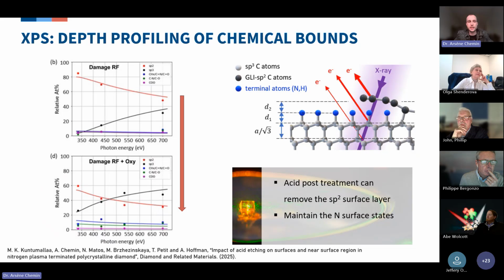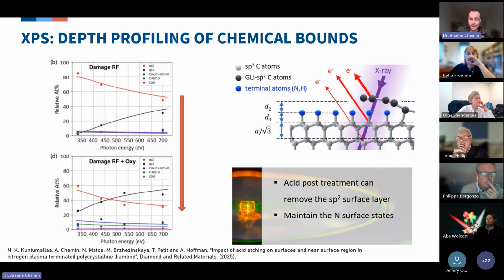Another thing that we can do is look at a different way to terminate the diamond. In that case, Alan also did some radiofrequency plasma, which was much more damaging than the microwave plasma that I presented before. You can see here that the amount of sp2 at the surface of the diamond is huge. So he decided to etch this sp2 surface, and you can see that after oxidation in liquid, this sp2 component was much reduced.